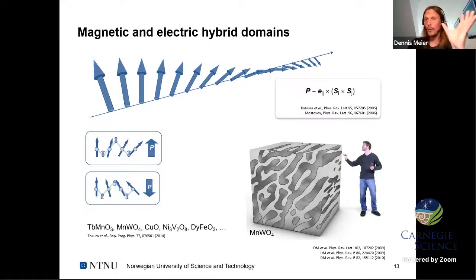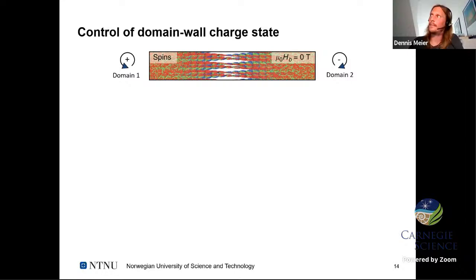The consequences then, I was talking about 2D systems and functional domain walls, is that we can get very unusual functional domain wall types in these materials. And I try to illustrate that here. I already mentioned that we have inversion symmetry breaking, and we will have domains with opposite chirality. On the left, for example, you have domain 1 with one chirality plus, second domain with chirality minus. And of course, you need to go somehow from the left to the right. Here you see micromagnetic simulations showing the spin system, where you basically see not very much. But if we break that down and look into the chirality, I already said this is a key parameter here. The chirality changes by continuously rotating across the domain wall.